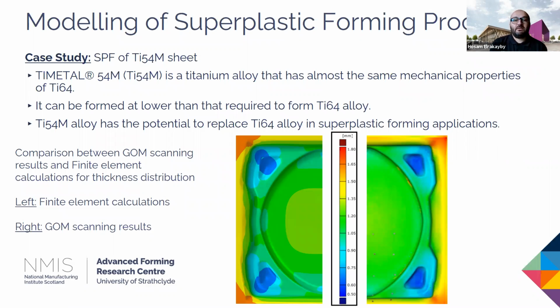So we have here Ti54M titanium alloy, which is developed by our tier 1 member, Timet. This alloy has almost the same mechanical properties as the well-known Ti64. It can be deformed at lower temperatures than Ti64. Therefore, there is a potential for Ti54M to replace the Ti64 in an SPF application.